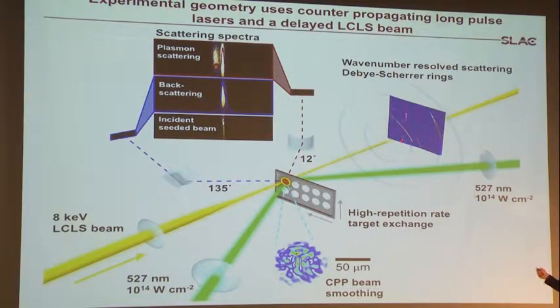You also combine these studies with wavenumber resolved scattering, and here you see the Debye-Scherrer rings in aluminum. And as the shocks are propagating through the material, the Debye-Scherrer rings disappear, and instead you see an ion-ion correlation peak, sometimes also called a liquid peak.